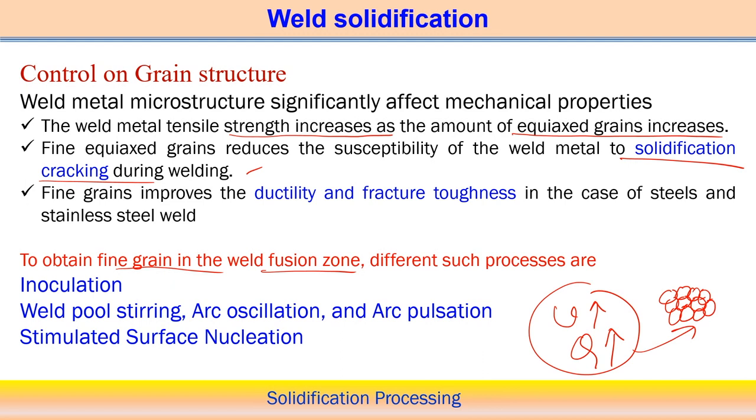And at the same time, whether the structure is fine or coarse will only be influenced by the rate of cooling. But if you reduce the G by R ratio in a welding process, it will promote the equiaxed structure. Whether it is a fine or coarse structure entirely depends on the overall rate of cooling of the component. But these are simple ways of understanding weld solidification, associated only with the fusion welding process, and it helps to get a better understanding and promote some control of the grain structure, just by understanding the solidification behavior of the welding process.